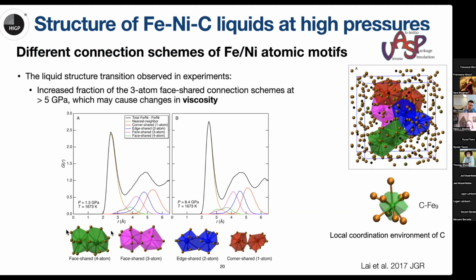From the calculation, we see that above 8.4 GPa, basically above 5 GPa, there is an increase in the fraction of these 3-atom connection motifs. As we know, this configuration is a stiffest configuration, so we should expect that there may be an increase in the viscosity if the liquid is above 5 GPa.